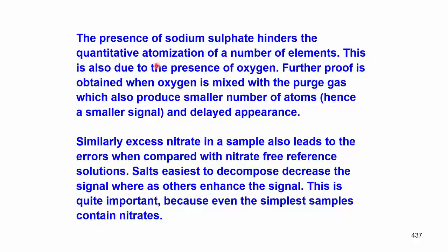We have found that the presence of sodium sulphate hinders the quantitative determination itself for a number of elements. If there is high sulphate, there is a reduction in the signal. This is due to the presence of oxygen.